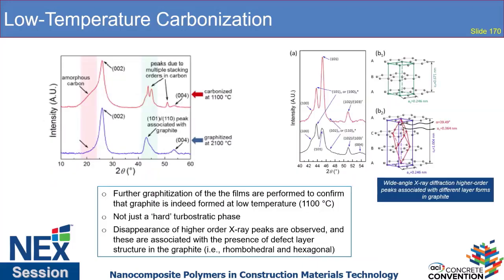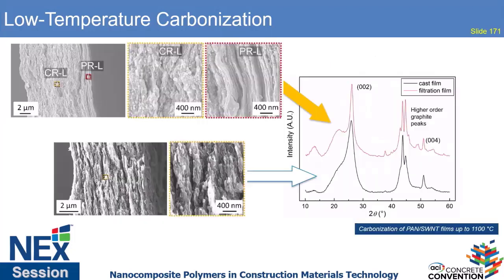But I show this because we were able to analyze the graphitic structures that we found with X-ray, and we can see that it's not the perfect hexagonal. There's some rhombohedral in there, but we are forming graphite. But what's really interesting is when I take those materials, one is, the bottom one here, is simply a film that I made that doesn't have any phase separation, and you see the carbonaceous structure, and this is the X-ray to prove that.